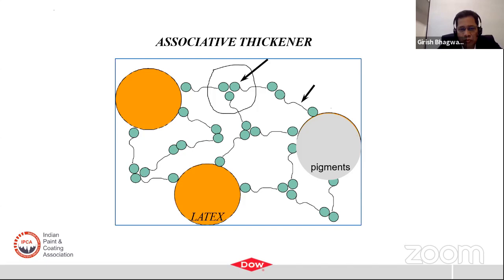So what are these? Basically, you can see those hydrophobes, the green ones, and there is a small chain. These are low molecular weight polymers as compared to the cellulosic or the conventional. So these hydrophobes end up associating with themselves or with the pigments and latex particles. So that's where the networking happens. And when the networking happens, it obviously will have resistance to flow and therefore viscosity. But these viscosities are not as high as with the conventional thickener, but it is high enough that it will not let the paint sag or have issues with respect to separation of pigments, etc. So that's what we want in premium paints.